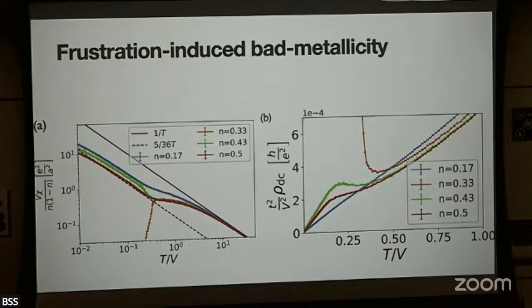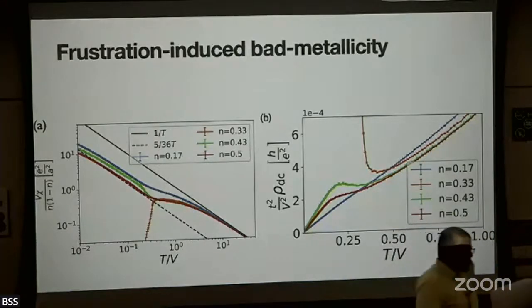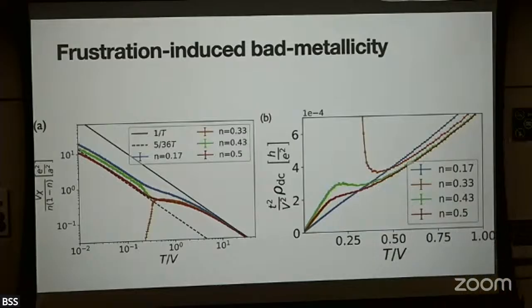So this is still high temperature, but this shows that the frustration, okay, because of strong electronic correlations, can give you new regimes of T-linear resistivity, but still no T-linear scattering rate. It's all dominated by the compressibility and strong correlations. So very different, presumably, from what we are after in the context of cuprates or TBG and so on, but interesting nevertheless, yes.